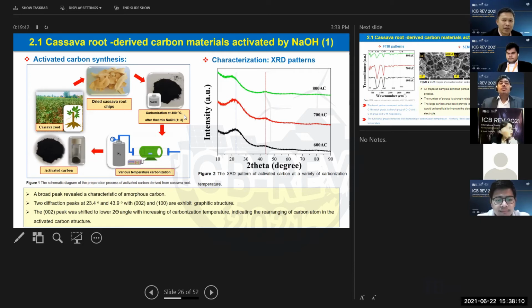The first one, we use sodium hydroxide. And for the second part, which I will tell you later on, we use potassium hydroxide as the activating agent. For the first one, this is the result of the carbon derived from cassava, and we use sodium hydroxide as the activating agent. And for the preparation, we start with the cassava root. We cut it into small pieces, and then we dry it.